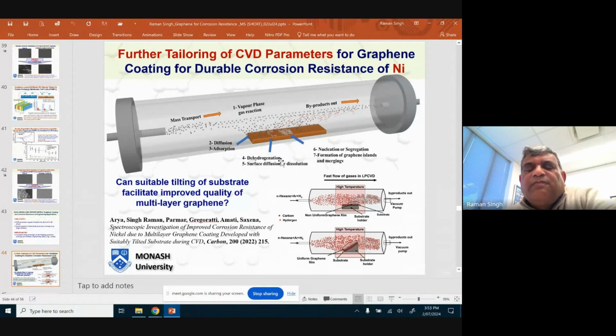This is the CVD chamber, and what we had been doing before this is that we were keeping the sample flat. So our new student who had just completed his PhD, Abhishek Arya, came up with the idea that if we keep it tilted, then on the basis of fluid dynamics, there will be a much more uniform distribution of the precursors over the surface. So we developed graphene under both 5-degree tilting and 45-degree tilting.